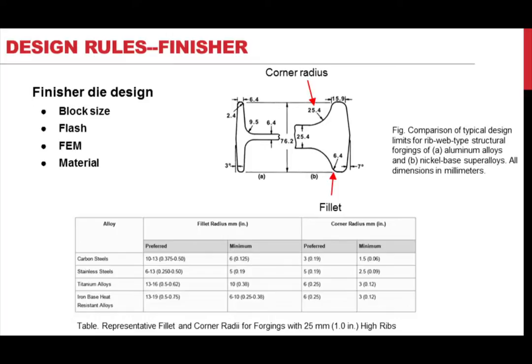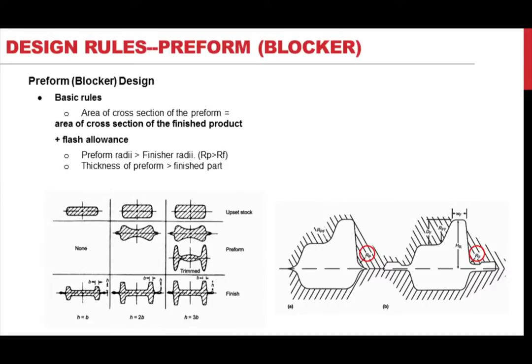As you see in the upper picture, the nickel alloy requires more radii and thickness in corners and ribs than the aluminum alloy. And the table underneath shows the representative radii for forging parts with 1-inch high ribs. For example, stainless steel is preferred to be forged with at least a 6 mm radius fillet, while for titanium it is 13 mm.